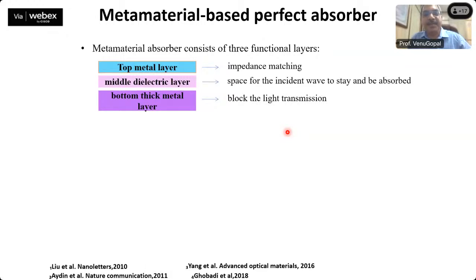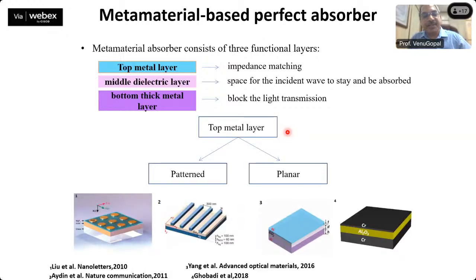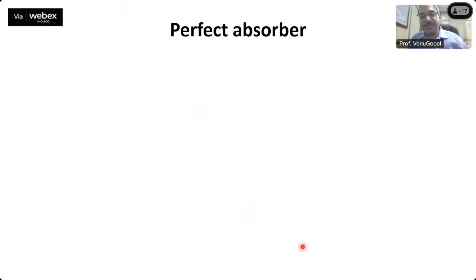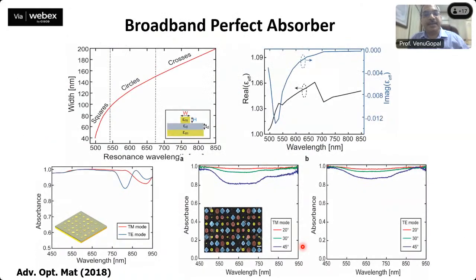Now coming back to the perfect absorber, we have the impedance matching layer, the middle absorbing layer, and the bottom thick metal layer to block the light transmission. The top metal layer can be patterned, like shown here, with 2D patterns or 1D grating-like structures, or they can be planar structures. I'll show one example where you can make it broadband by choosing scattering elements having different shapes for different wavelength regions. So squares for this region, circles in this region, or crosses or diamonds for this region, and arrange them in a square lattice with randomly distributed shapes.